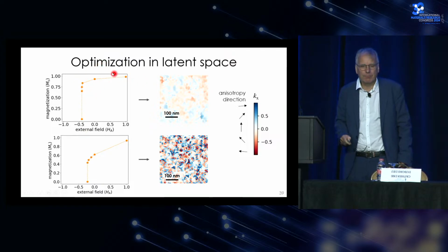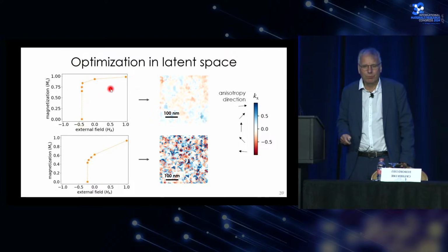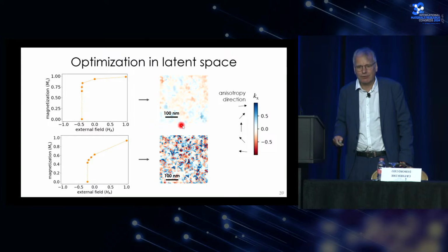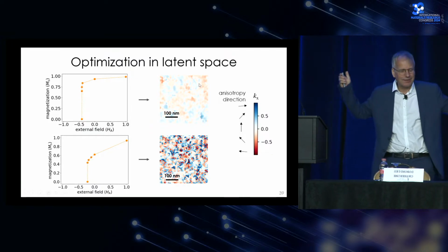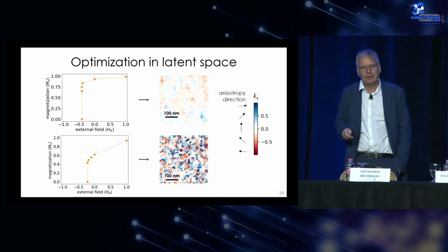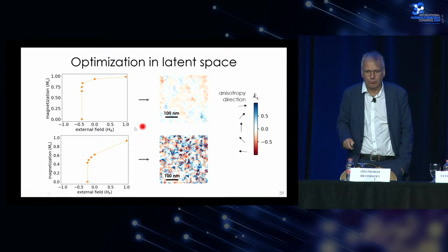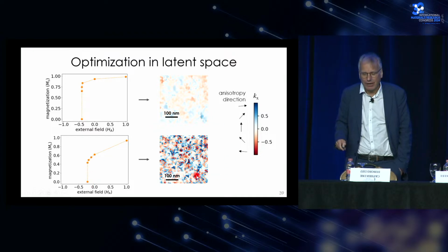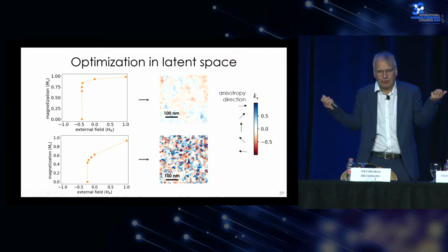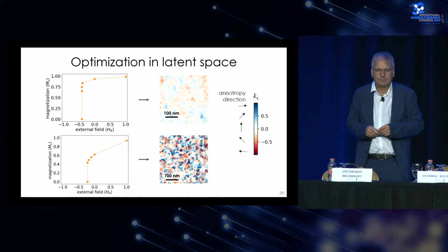So here are two examples. This is one magnet with a very square hysteresis loop, and we get this microstructure where all the grains are almost perfectly aligned. Then we have as input this very steep slope, and we get as microstructure a magnet where we have much more misalignment.